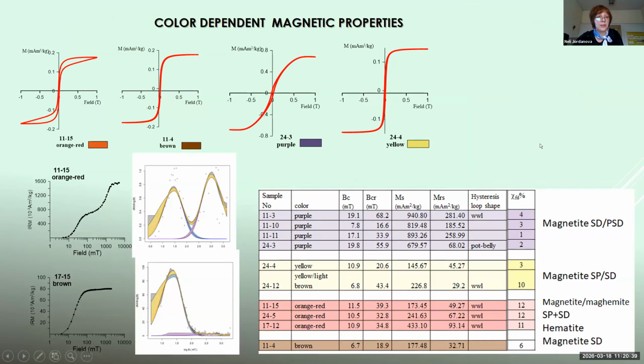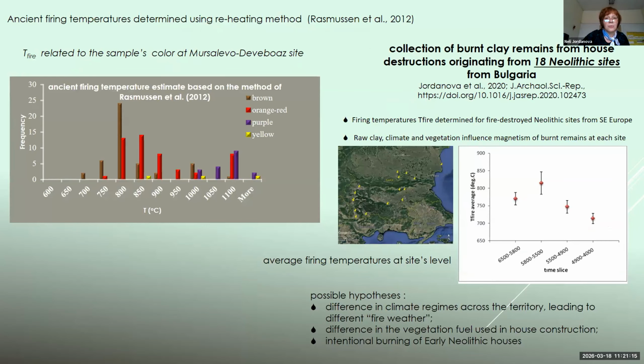So we did detailed magnetic characterization of the different materials from many houses. And we obtained a clear relation of magnetic properties to the prevailing color of the materials, with the presence of stable magnetite in purple and yellow materials, while orange, red materials, of course, contained also hematite. For the collection, we also retrieved the ancient firing temperature using the reheating method. And this is the summary of the data we obtained.